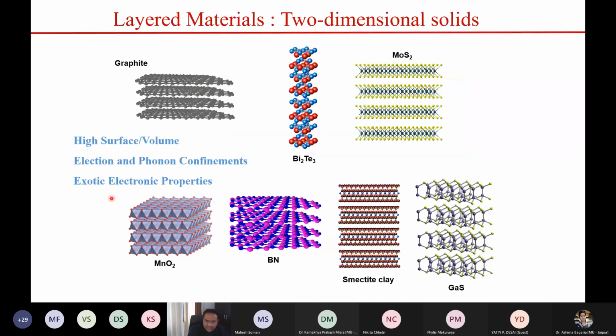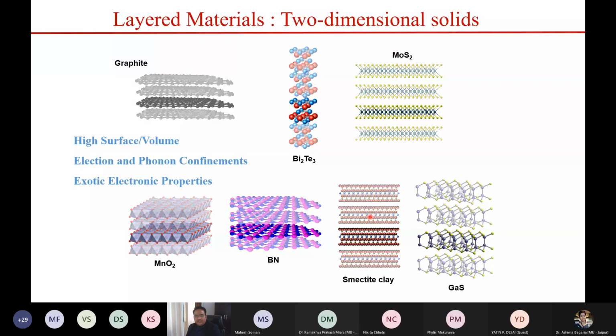These layered structures are equivalent to graphene, which you know is a monolayer, a single carbon layer of graphite. So if you have graphite and you exfoliate a single layer of the graphite, you get graphene. These are materials made up of layers of atoms, and the layers of atoms are attached to each other by van der Waals forces. So what I'm talking about is that these are the monolayers, and there is a gap in between. This is the van der Waals gap, and it exists in all these layered materials. And so you can exfoliate down to the atomically thin layer.